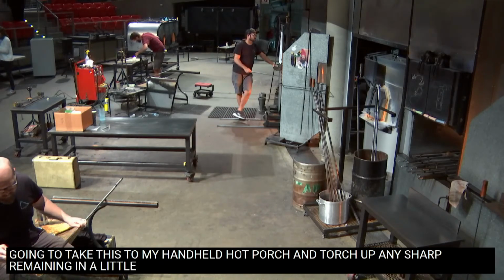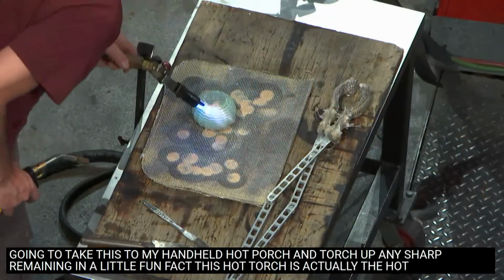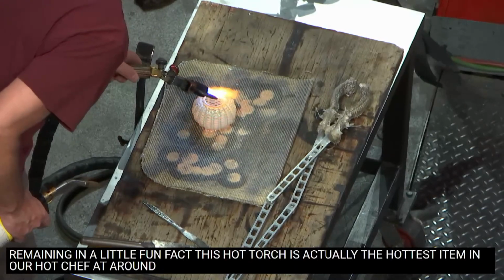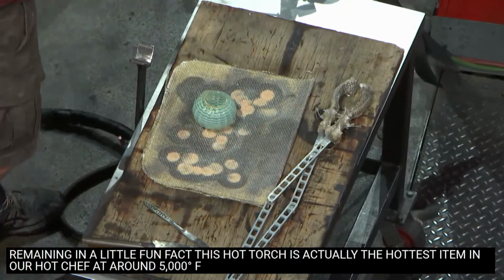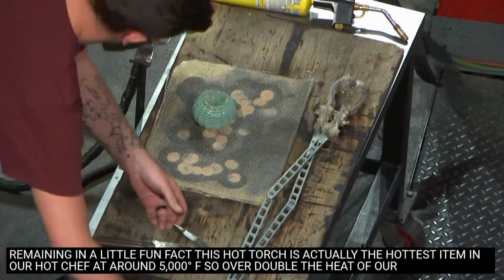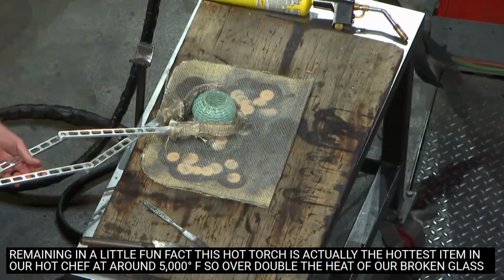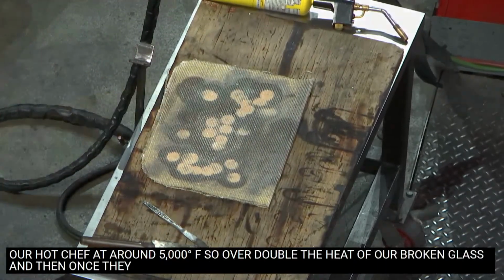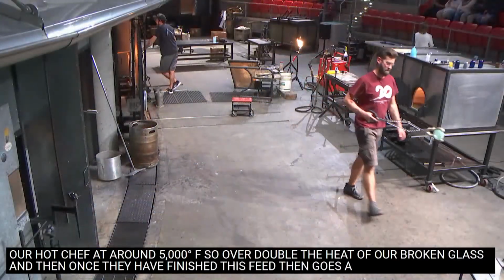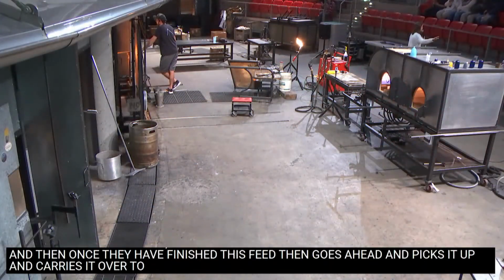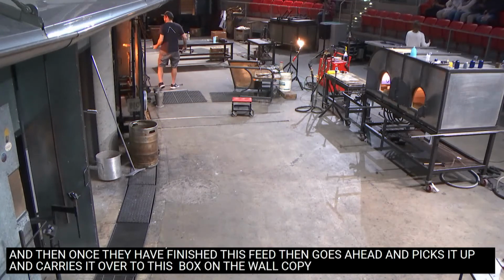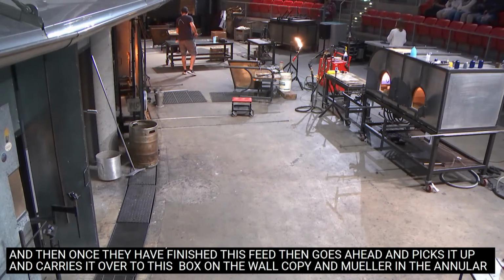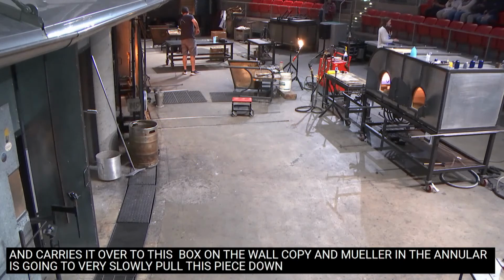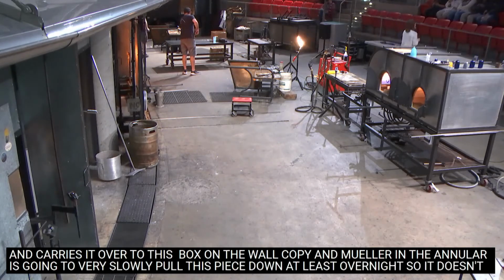And a little fun fact, this hot torch is actually the hottest item in our hot shop at around 5,000 degrees Fahrenheit, so over double the heat of our molten glass. And then once they have finished this bead, Ben goes ahead and picks it up and carries it over to this big black box on the wall called the annealer. And the annealer is going to very slowly cool this piece down at least overnight so it doesn't break due to thermal shock.